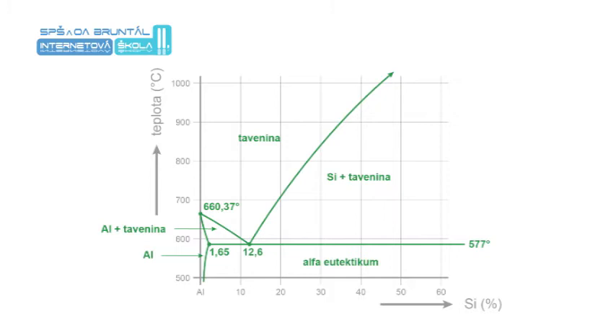For aluminum alloys, inoculation and modification are predominantly performed. The goal of inoculation is refinement of the primary phase. Grain refinement results in improved mechanical and technological properties. Inoculation is performed primarily with titanium or a combination of titanium and boron.